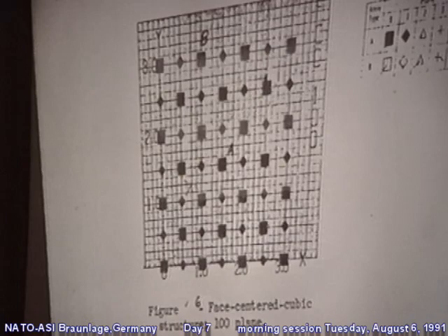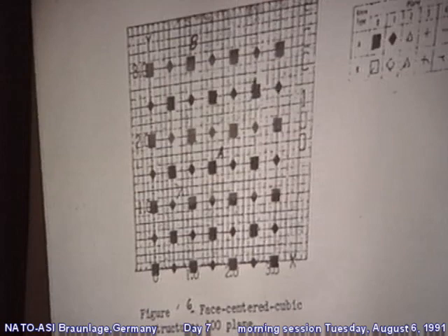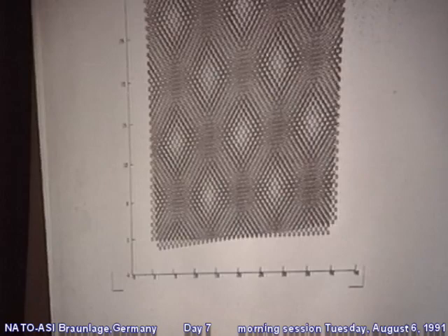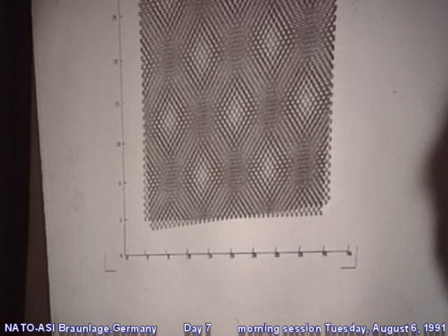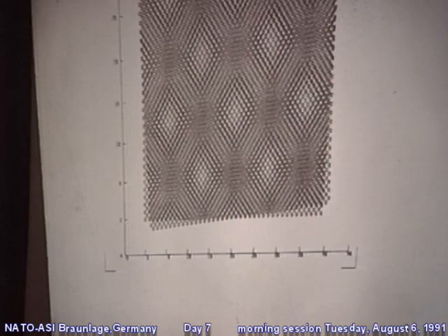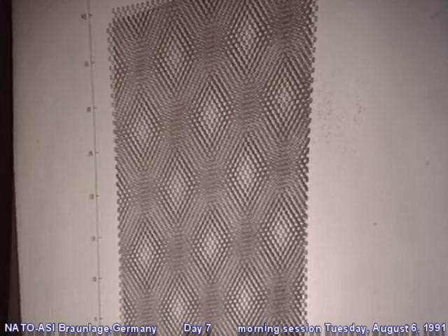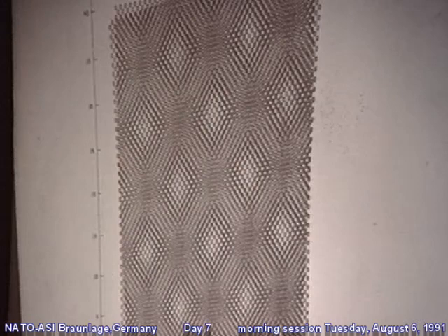Let's consider a very idealized situation. This is an FCC 100 surface. The squares are the top of the surface atoms, and the rotated squares are the next layer down. Let's consider the interface between the top plane and the next plane down. Suppose you just take that interface and twist it four degrees — you see the situation changes from a very nice picture to an extremely complicated picture. This shows the problem in trying to do first principles calculations on this particular system, because now you have really no simple periodicity to take advantage of.